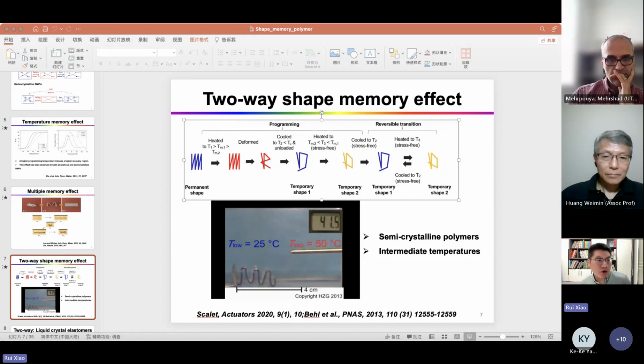You have a semi-crystal polymer, you deform it to a temporary shape, you cool down to low temperature to fix this temporary shape, and now you increase temperature. You cannot increase to very high temperature—if you do, you will not get the effect. You increase temperature to an intermediate temperature, and now you can have two shapes in between these two shapes.